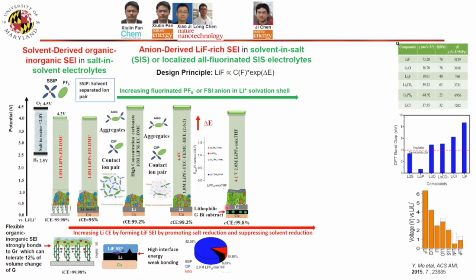And this is not only for lithium metal. Any anode with a high volume change works on the same principle. And then we tried micro-size silicon. Silicon at micro-size, everybody believes, is really, really challenging. But we use this design, we validate, we use micro-silicon, and we can reach 99.9. By micro size, we mean more than 10 micron, even 20.